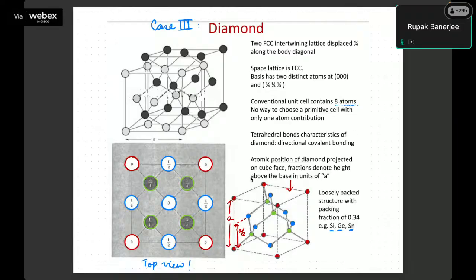Now if you get rid of this double entwined structure, you will see that there are actually carbons sitting, some on the halfway path and some at 1/4 and some at 3/4. So there is one carbon which is here, which is 1/4 from the base. One carbon which is here, which is 3/4 from the base. One carbon which is here, which is at the face. One carbon which is at the bottom. So if I look from the top view, this is a top view.